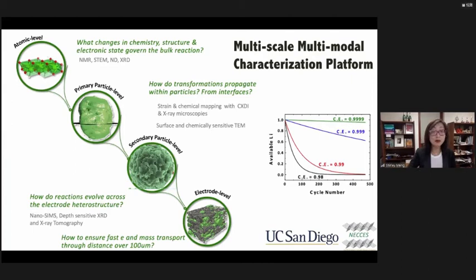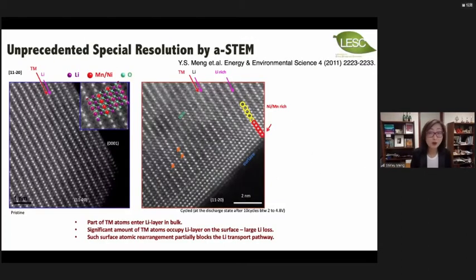So a good example to show you is my work, this is almost 10 years ago. I mean, it's exactly 10 years ago. But at that time, we were thinking about how we can utilize the atomic resolution scanning transmission electron microscope. I mean, 10 years ago, it was not very common for people to use this kind of so-called very fancy tools to look at the surface of high voltage cathode materials. And before and after, here you're seeing very beautifully synthesized cathode particles where you have a layered structure. We call it a layered structure by cartoon, and actually you can observe it in the microscope.